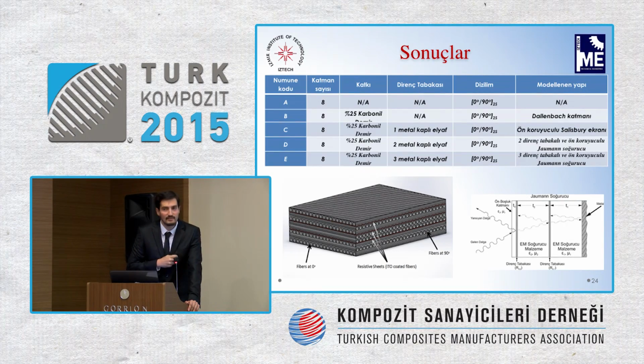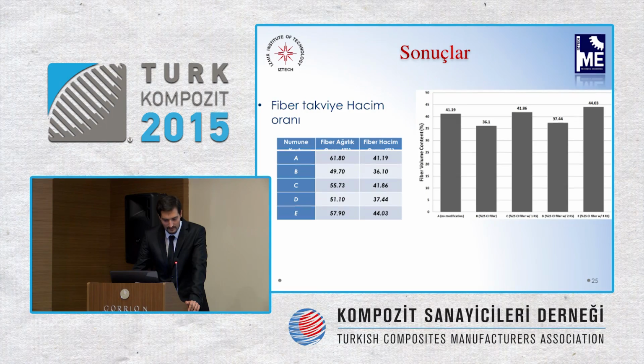We have 5 structures, and the number of layers is 8 in all of them. The configuration can be seen here, and you can see the resistive sheet. The fibers are here, and the mid-plane is symmetrical. The first one is a reference sample. There is no add-on, no additives. On B, we have carbonyl iron, equaling the Dallenbach layer. On C, it's carbonyl iron, and we have 1 metal coated fiber. On D, there are 2 metal coated fibers, and on E, there are 3 metal coated fibers.